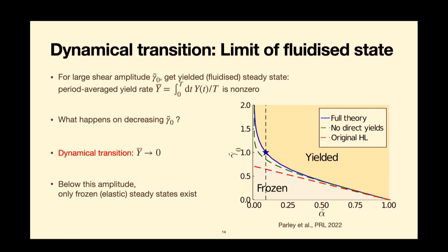So what do we get out of this kind of theory? So the one thing that we can do more analytically is we can prove that this model really has a dynamical transition of the type you see in the simulations. So there really is a distinction between how the system responds at high amplitudes up here and low amplitudes. At high amplitudes you get these yielded steady states. At low amplitudes you only get what we call frozen states, so states which just move elastically.